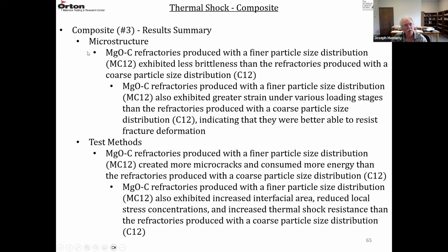So in this work for the microstructure, the MgO carbon refractories that were made with the finer particle size distribution, that was the MC12, were less brittle than the refractories produced with the coarse particle size distribution. And the refractories produced with the finer particle size also exhibited a bigger strain under the various loading stages than the refractories with the coarse particle size distribution. So they can withstand greater strain. They're going to better resist thermal shock fracture.